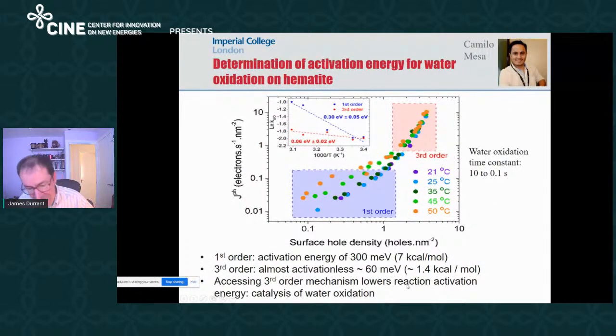To give you an example of how we can take that sort of study further, then a rather easy thing is we can change the temperature. And what we observe when we change the temperature, we measure the flux of water oxidation versus surface hole density. At low hole densities, the reaction accelerates. And we can apply an Arrhenius analysis, again, an activation barrier of about 0.3 electron volts.